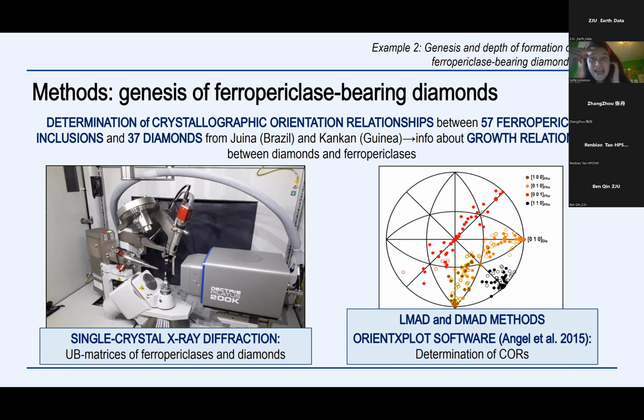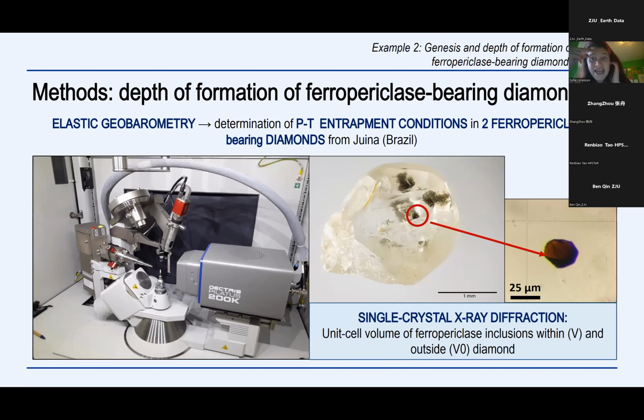And this determination was done between 57 ferropericlase inclusions and 37 diamonds. And these diamonds come from both Juína in Brazil and Kankan in Guinea. And for the depth of formation, on the other hand, we applied the elastic geobarometry on only two ferropericlase-bearing diamonds coming from Juína in Brazil to determine their possible pressure and temperature conditions.